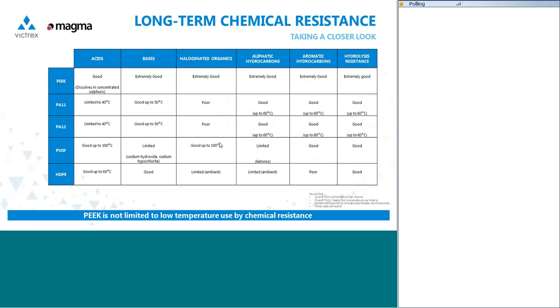So here I've basically set out 6 broad brackets of chemicals, and I'm comparing the polymers that we've just been looking at in terms of mechanical properties. I'm just comparing their chemical resistance. I guess firstly the key thing to notice is that PEEK, and I'm sure you're aware of this because, as I said earlier, it's been around 30 years or more, has exceptionally good chemical resistance across the board, really, right from highly sour fluids right through to acids and so on. So really good chemical resistance, and there isn't a solvent for PEEK below 200 Celsius.